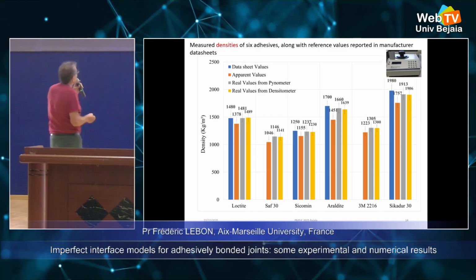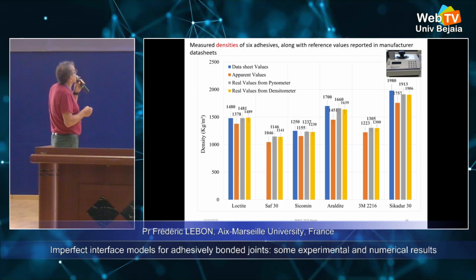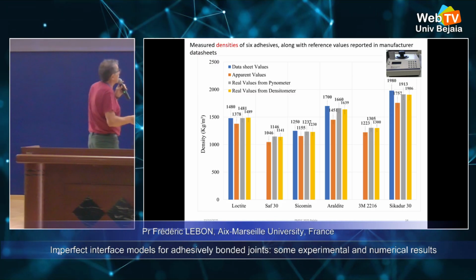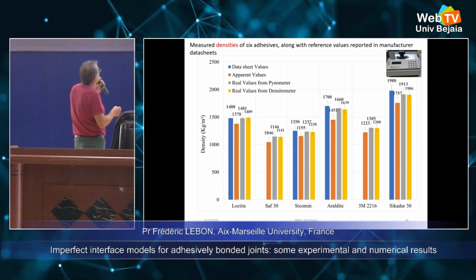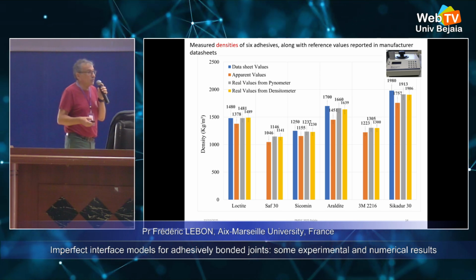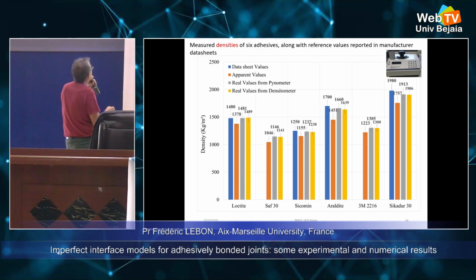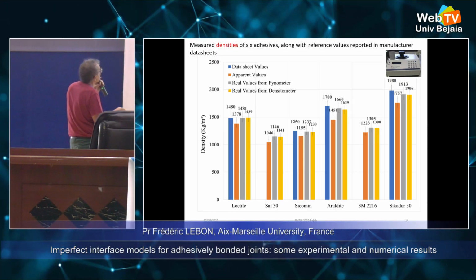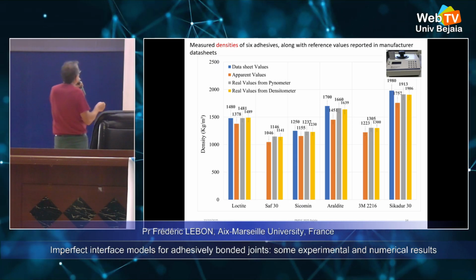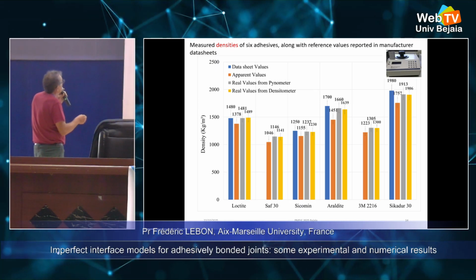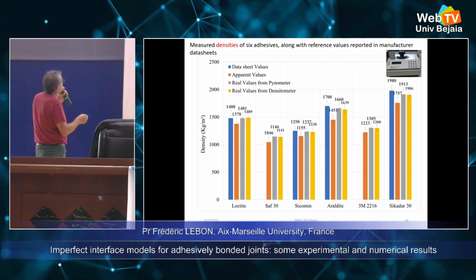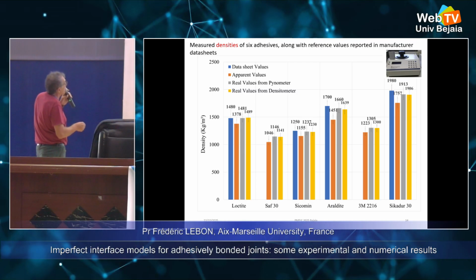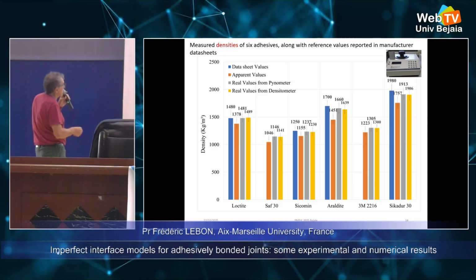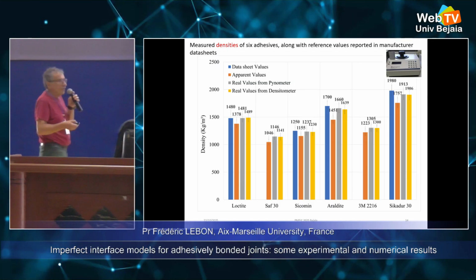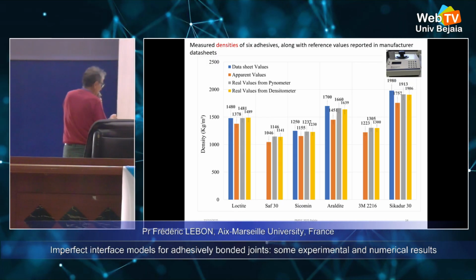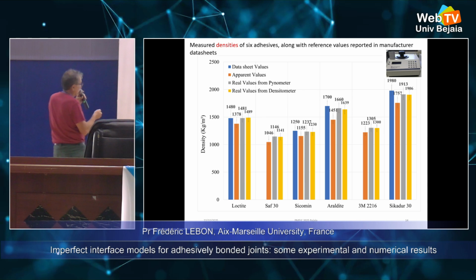Another kind of results for densities for 6 adhesives, we can compare 6 adhesives. We have the datasheet value given by the industry, and we have different kinds of experiments. We have 3 kinds of experiments using pycnometer, densitometer, and here is only with the mass. And we can compare the six glues which are epoxy, polyurethane, and so on. And we can compare for the density.